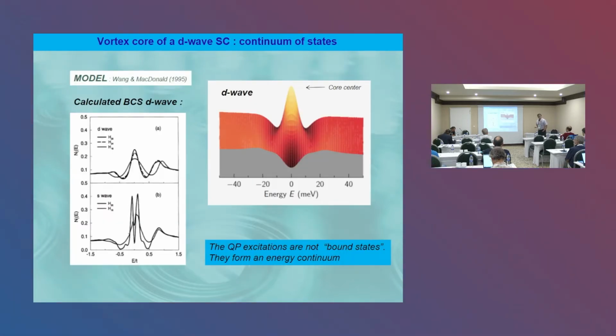But cuprates are not S-wave, but D-wave superconductors. And so calculations have been performed also in that case. A long time ago, Wang and MacDonald predicted that, similarly to the case of an S-wave superconductor, the center of the vortex core should also reveal a zero bias anomaly. And the evolution is actually quite similar to the one of the S-wave superconductor, with the split of this zero bias anomaly while going away from the core center. The main difference between the D-wave and the S-wave is that there are no bound states here. Whatever you go at low temperature, you will never see individual bound states. It's a continuum of states.